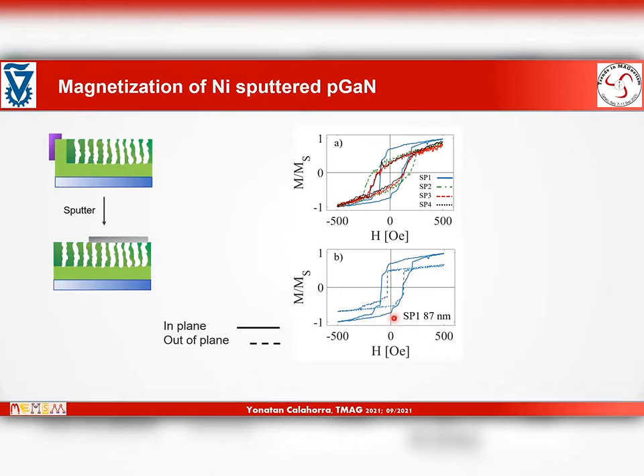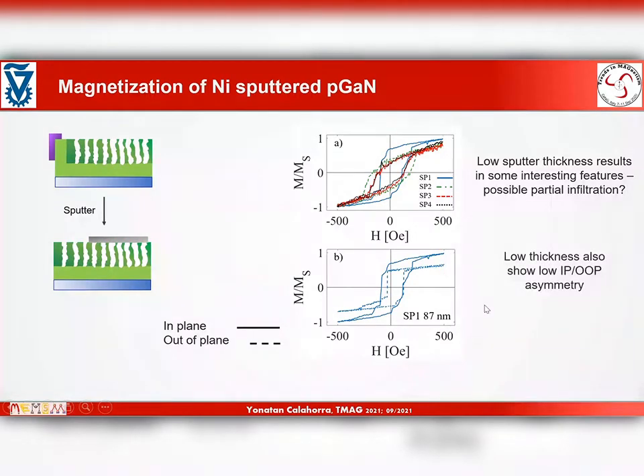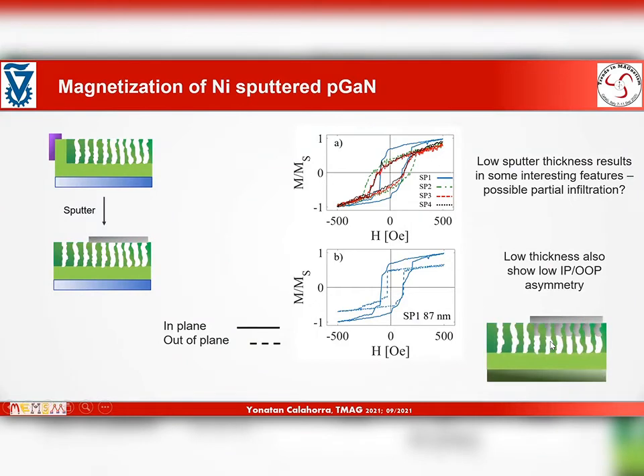interesting features here in coercivity, but we also see lack of the in-plane, out-of-plane asymmetry. And basically we think that some nickel penetrates the top of the porous layers, and if the total film thickness is relatively low, then the contribution of this infiltrated layer is stronger.